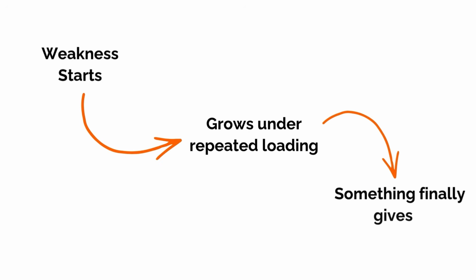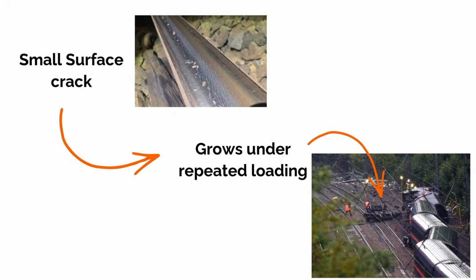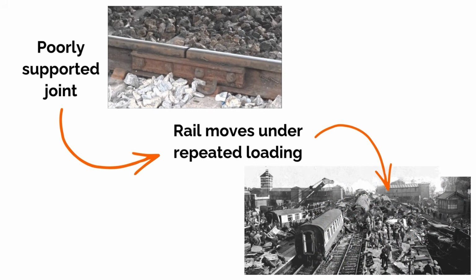Some examples of these combinations could be: a small surface crack begins at the wheel-rail contact point. Traffic keeps growing it. If grinding, inspection, or replacement doesn't happen in time, it can become critical. Hatfield, in 2000, is the starkest reminder of what rolling contact fatigue can become when intervention comes too late. A joint is poorly supported. The rail moves more and more under each wheel. Repeated bending and impact lead to cracking and eventual failure. Hither Green, in 1967, showed how a broken joint could lead to a catastrophic consequence.